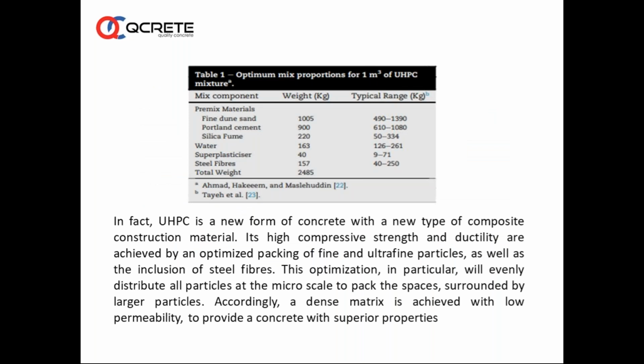In fact, UHPC is a new form of concrete, a new type of composite construction material. Its high compressive strength and ductility are achieved by an optimized packing of fine and ultra-fine particles as well as the inclusion of steel fibers. This optimization in particular will evenly distribute all particles at the micro scale to pack the spaces surrounded by larger particles. Accordingly, a dense matrix is achieved with low permeability to provide a concrete with superior properties.